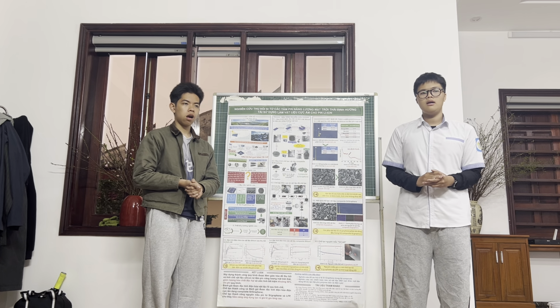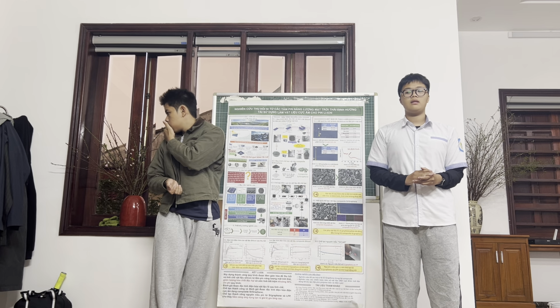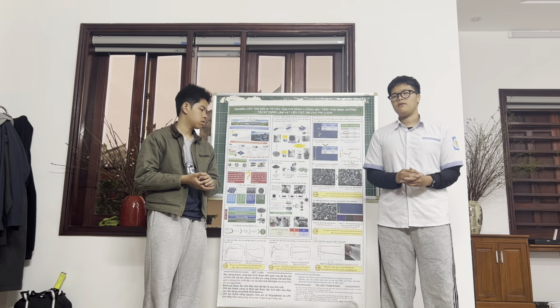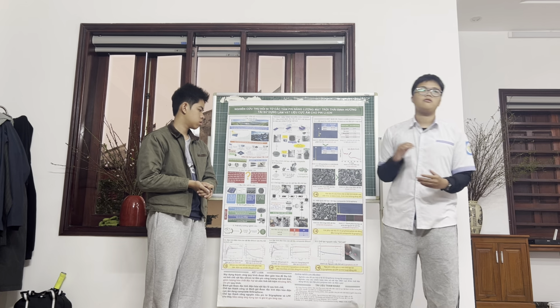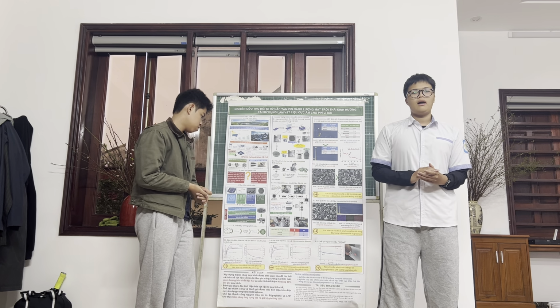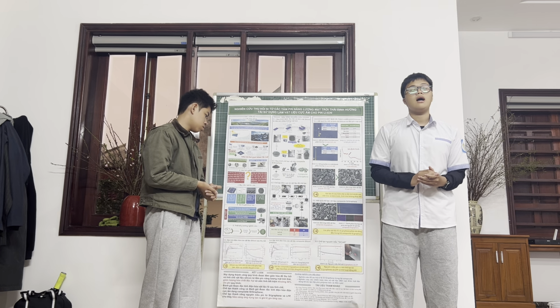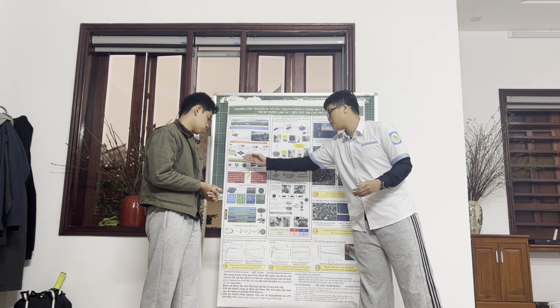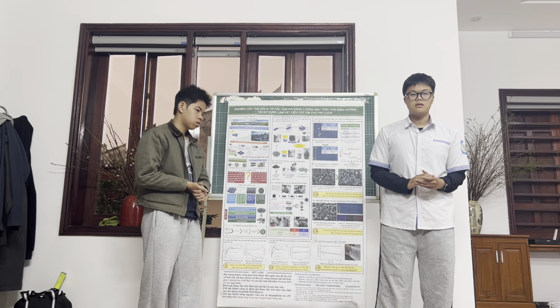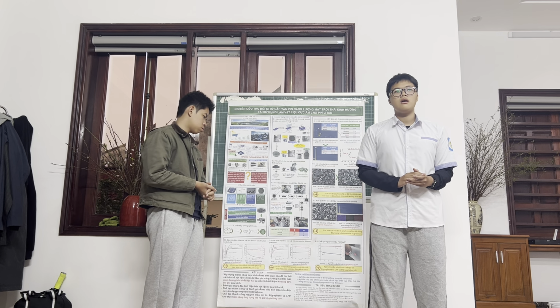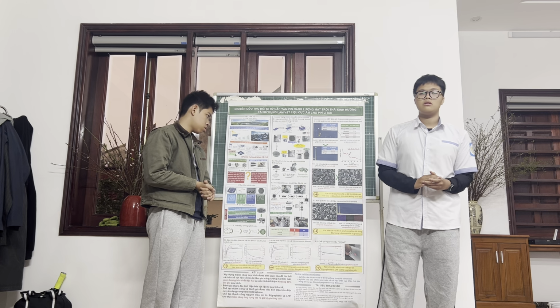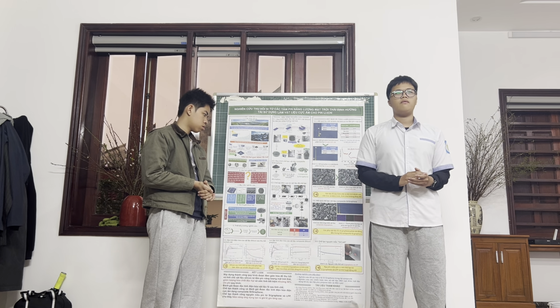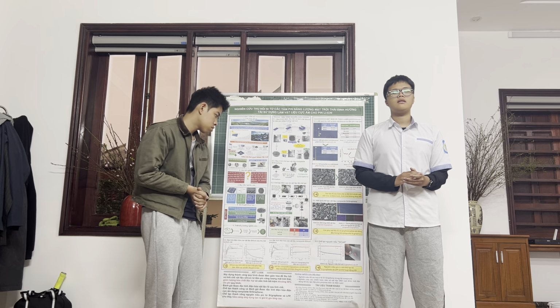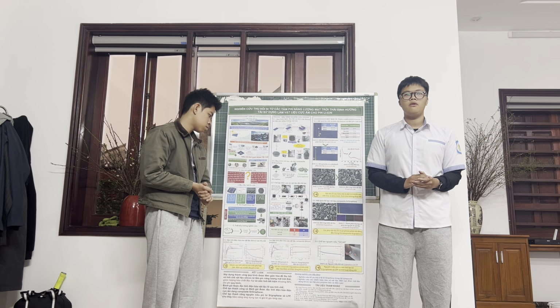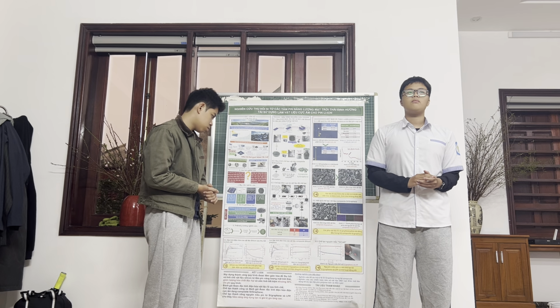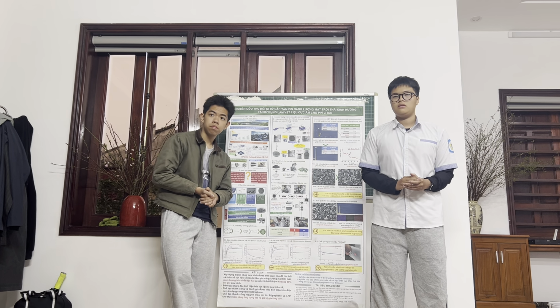For this application, silicon does not require high crystallinity and can even tolerate the remaining impurities. As a result, the cost of the refinement process, which accounts for up to 70% of total cost, can be significantly reduced. Drawing from this practical background, our team has chosen to research the recovery of silicon from decommissioned solar panels for repurposing as anode material in lithium-ion batteries.